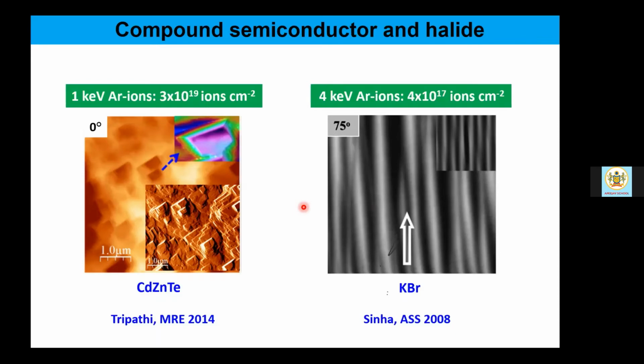To have the best feel, it is very important that we gauge into a large number of visuals, pattern formation which are reported in various materials. So here is the example of 1 keV argon ion bombardment on an important II-VI material, cadmium zinc telluride, CdZnTe. And the right frame is an example of 4 keV argon ion bombardment on a halide material, potassium bromide.